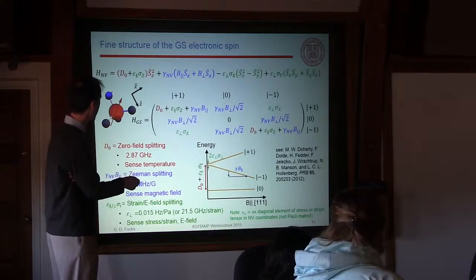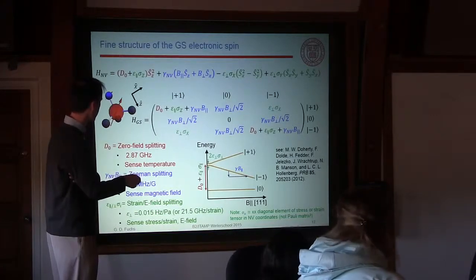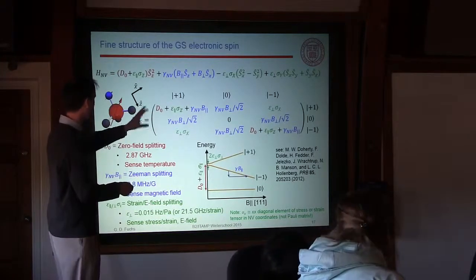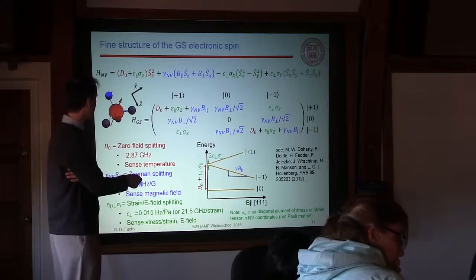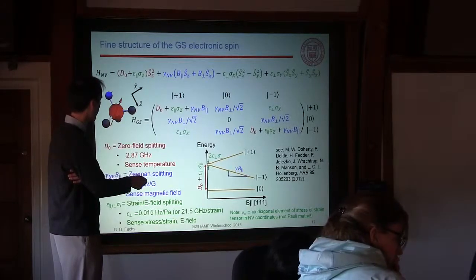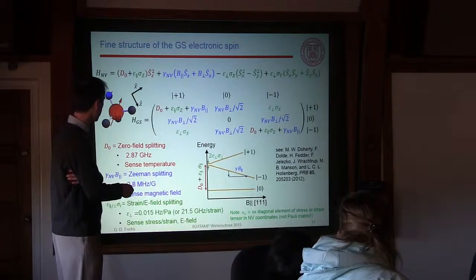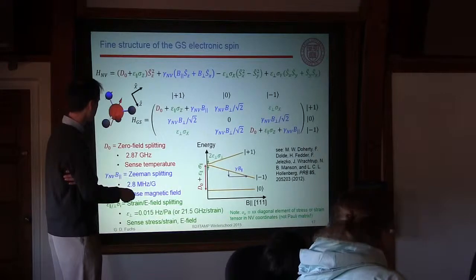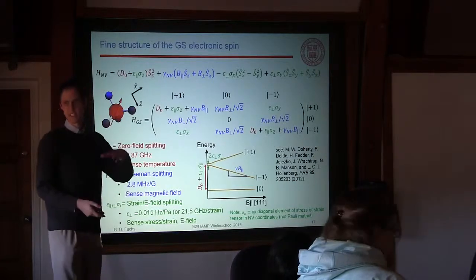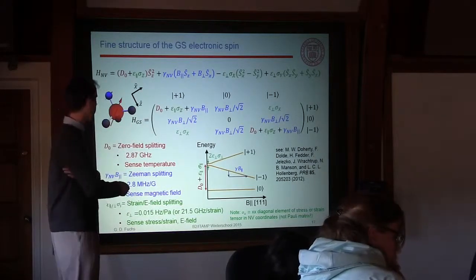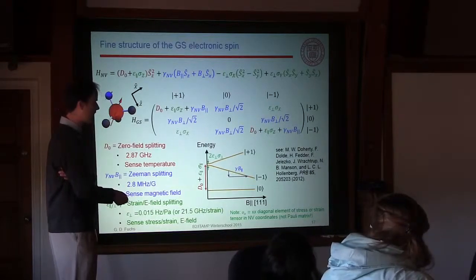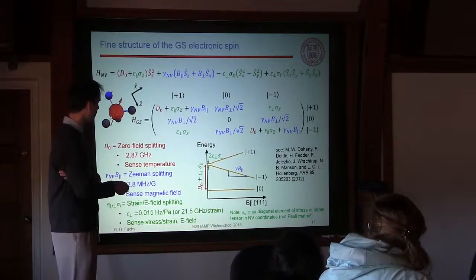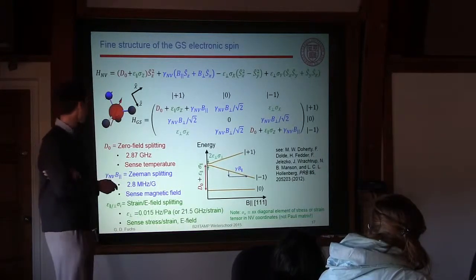And these two both end up, so in this off-diagonal term, I've only included one of these. The other one would come in with an i, but essentially it's the same thing. And they couple together minus 1 and plus 1. So at zero magnetic field, what this perpendicular stress coupling does is it lifts the degeneracy between minus 1 and plus 1 and creates the states plus and minus, just symmetrized versions. Now, if you apply a large magnetic field to go back into the Zeeman basis, it's still there, it just doesn't very much shift the energy levels of these spins.